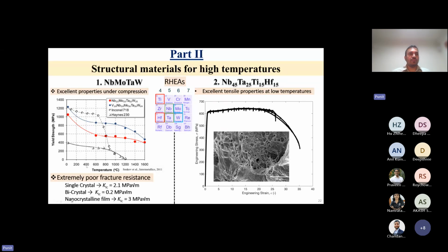Although there are some studies where they investigate single crystal, bicrystal and nanocrystalline film, and the fracture toughness, if you see those values, they are relatively much lower compared to what I was talking about in FCC alloys. And even in case of niobium, tantalum, titanium, hafnium, we see this material actually showing a lot of ductility and uniform strain, about you can see here about 15%. And this material actually fractures by microvoid nucleation and coalescence.